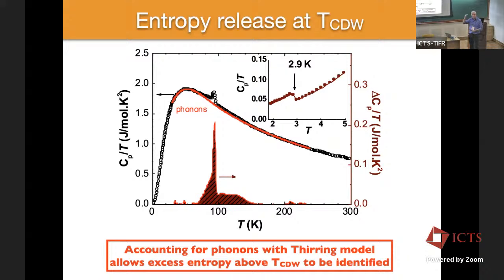And then you're going to look for the difference between the actual data and, if you like, the simple lattice contribution to the heat capacity, which is actually most of the heat capacity. But if you do that subtraction, then of course you get this big peak at 94 Kelvin, but there's a foot associated with the thermodynamics above the phase transition, which goes out to about 150 Kelvin or so. And we believe that this is the entropy associated with the fluctuations which we're seeing in the low resolution X-ray scattering measurement. So we think this is quite consistent. And I'll show you in a minute that it's consistent with other examples as well.